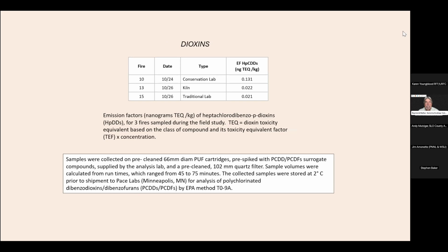And then finally, looking at the dioxin, we got fairly low measurements for dioxins. The samples were sent off to a lab in Minnesota for analysis, and dioxins are expressed in units of TEQs, which are toxicity equivalence, which is based on the toxicity of the specific compound that we are looking at. So it's a little different from regular emission factors. But anyway, we only were able to do 3 for the field. We did more for the lab, which I will show later, but the results were low.